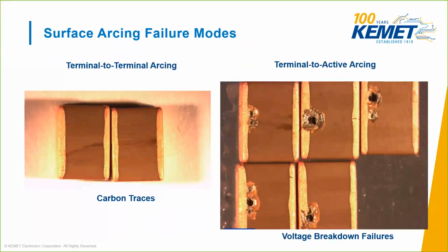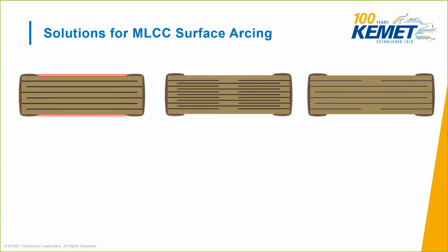Here we can see the difference between the terminal-to-terminal arc versus a terminal-to-active electrode arc. On the left, we see a terminal-to-terminal arc resulting in carbon traces between the two terminations, which can result in a lower insulation resistance. On the right, we can see terminal-to-active electrode arcing, and that can achieve dielectric breakdown and a catastrophic failure. Now, there are three possible solutions for MLCC surface arcing.